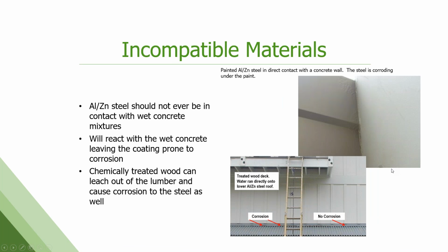The other incompatible materials we run into a lot is zinc aluminum. Steel should not ever be in direct contact with wet concrete. The moisture from the concrete, that alkaline condition that exists, attacks the aluminum and allows corrosion to start. There's an example here of concrete that was up against the painted zinc aluminum panels. This is the same house with the stainless steel lights in the prior slide, unfortunately.